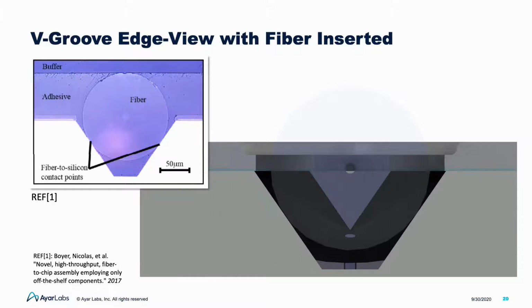In the inset figure, note that the fiber is surrounded by adhesive. This is the same aforementioned adhesive that both secures a fiber to the V-groove while also participating in the optical performance of the coupling. Given the proximity of the spot size converter, the adhesive will also fill that region as well. Therefore, it will be important to control the adhesive's viscosity and propensity for capillary flow.